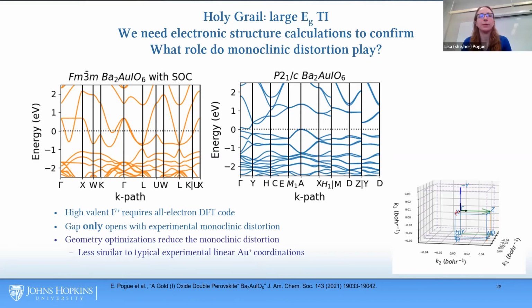Yeah, also, another thing I realized I hadn't talked about, but I thought was interesting. With the gold coordination, typical gold plus coordinations tend to be more linear. Whereas in the double perovskite structure, the coordination is octahedral. And so that was another thing that was pointing to there likely being some deviation from perfect octahedral, which ended up being the case, which we were seeing in both Raman and X-ray and neutron.